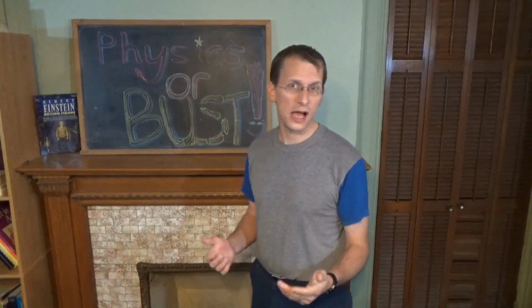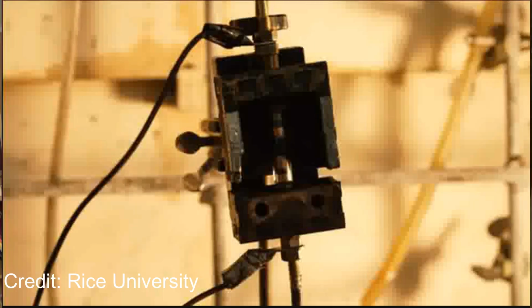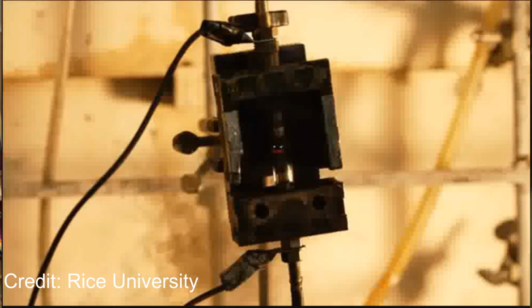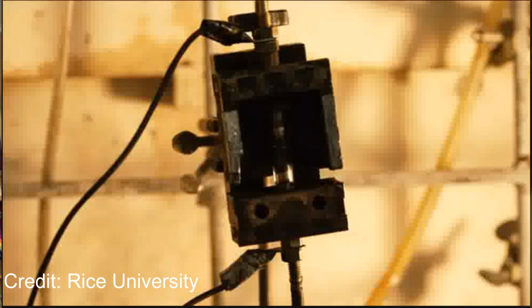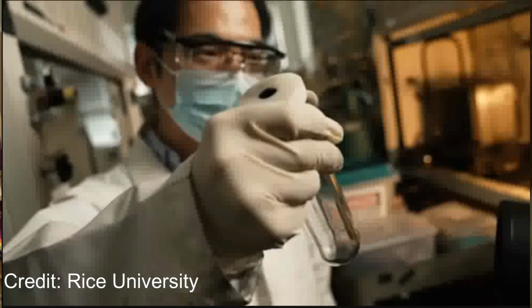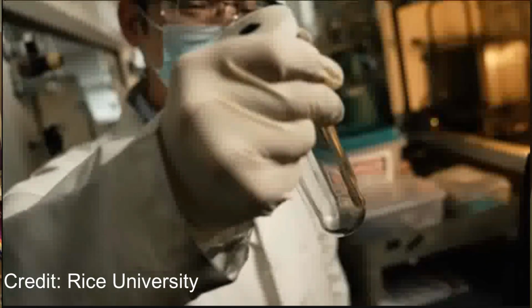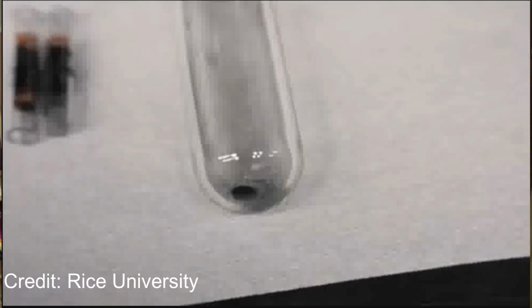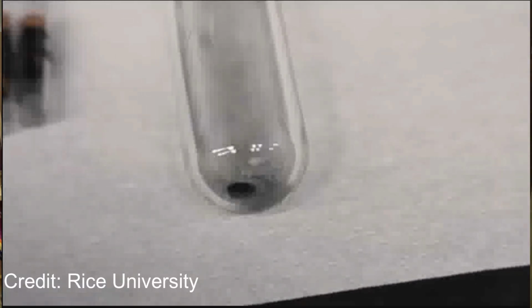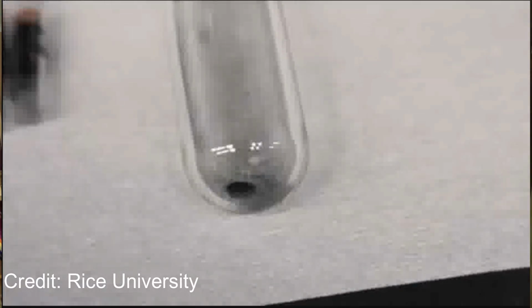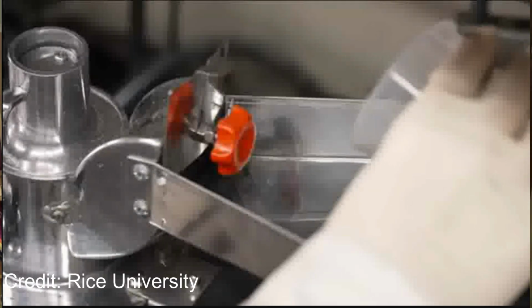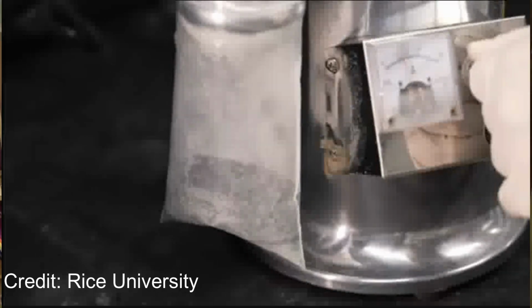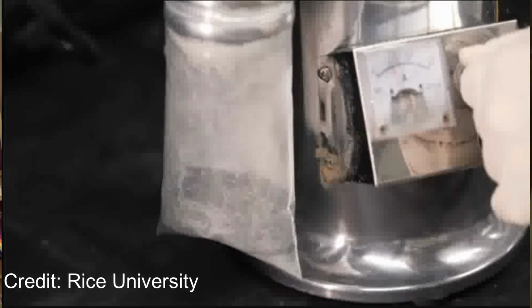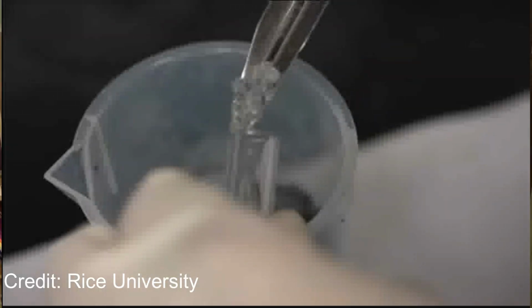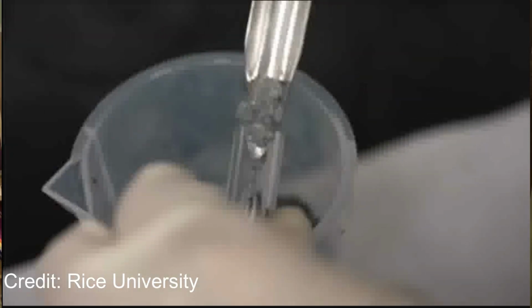The second is non-equilibrium pathways. Because the heating and cooling are so fast, the material doesn't have time to reach equilibrium. That lets you access reaction pathways and products that are thermodynamically possible only at extreme conditions and are kinetically trapped when you cool quickly. In this case, lithium is driven into chloride form and remains mobile. Heavier transition metals end up in oxidized, less soluble forms.